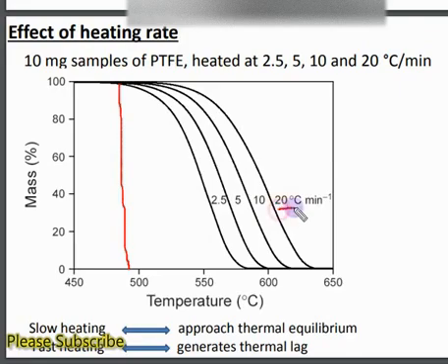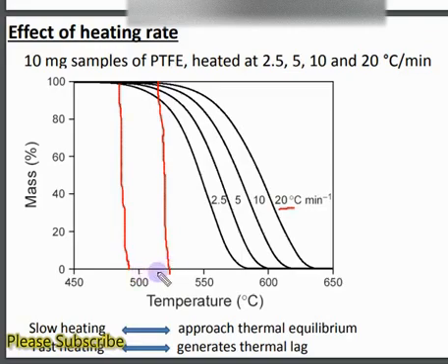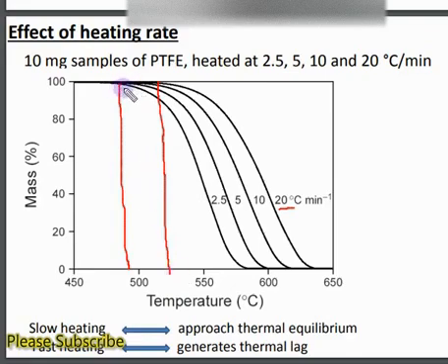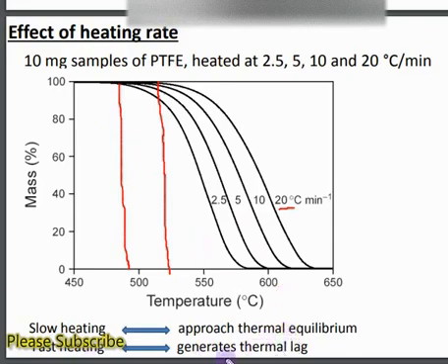For the same material, by changing the heating rate to 20°C per minute, the same event occurs at a higher temperature — about 510–525°C. So the same thermal event for the same material occurs at two different temperatures depending on the heating rate. This is due to the faster heating rate generating thermal lag, whereas a slower heating rate approaches the thermal event more accurately and is preferred.